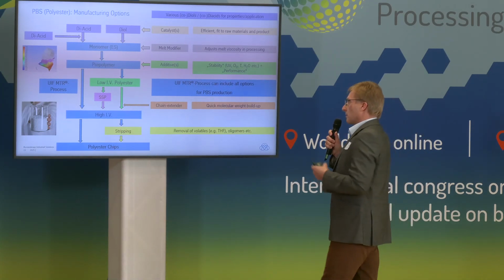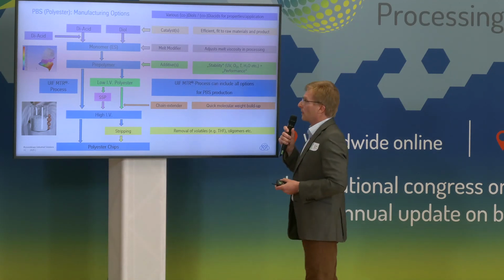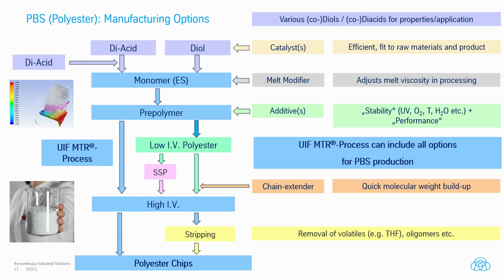After you made the pre-polymer by applying some vacuum, you should consider if you want to add some additives. Additives which give you better functionality. Additives which control your stability against UV light, against oxygen, temperature, and water.